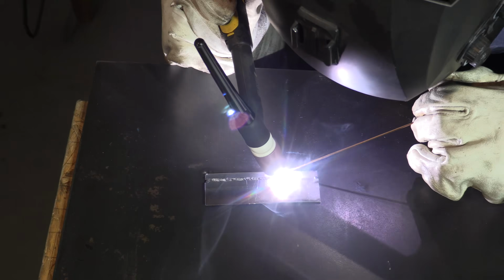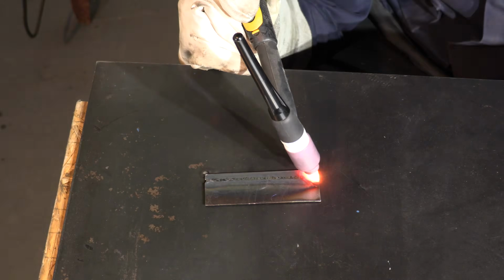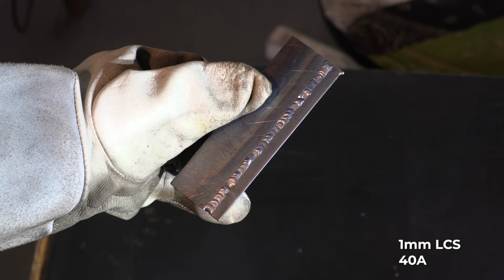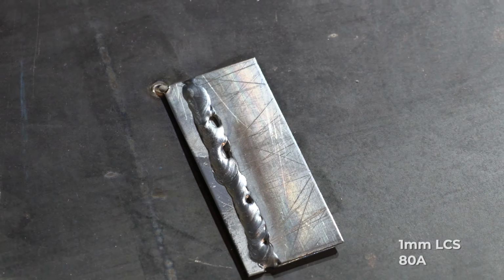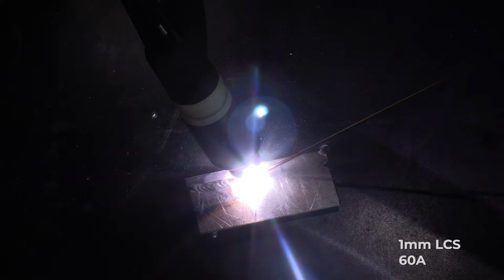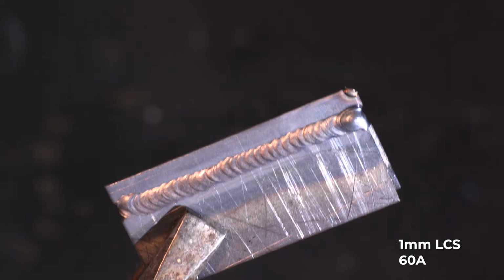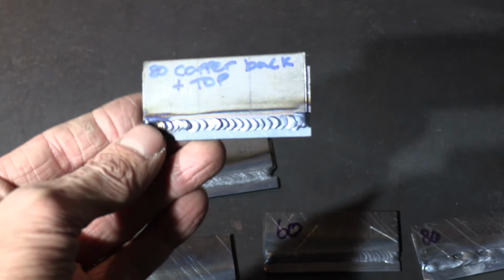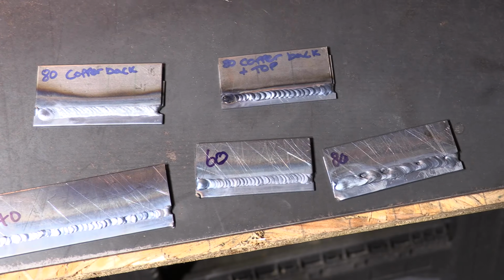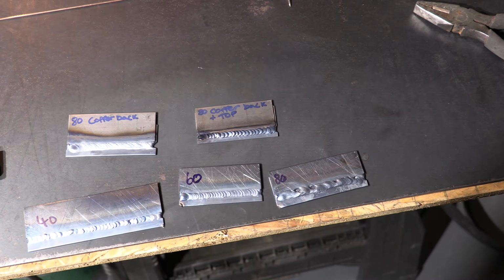Let's compare several more welds at different amperages. One at 40 amps, one at 60 amps, and one at 80 amps, all without copper chills. The 40 amp weld is underpowered, while the 80 amp weld runs too hot. The 60 amp is closer to the ideal setting for this joint. Now, when we repeat the 80 amp weld, but use copper chills on both the back and top surfaces, the results significantly change. Even though the amperage is higher, the weld quality improves.